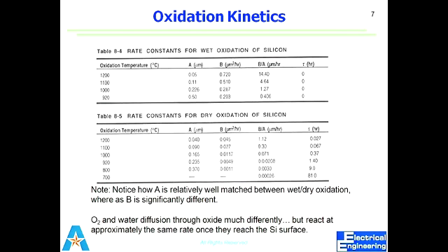If I want the oxygen gas supply to get into the furnace, F1 would not be a limiting factor. We learned this: it's always the diffusion control or the reaction rate control. It's never the transport control. So F1 is never the factor unless I want it. I can give as much oxygen as I can, but I cannot let all the oxygen diffuse through. I cannot make it possible for all the oxygen to react with silicon at one time. So that is the diffusion control or the reaction rate control. The transport is not a problem.